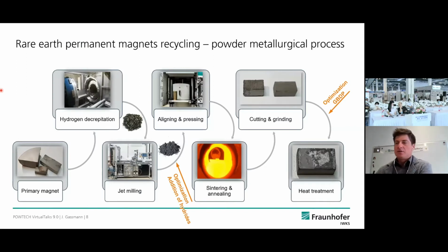So we heard a lot about powder milling and about particle size measurement today. Here the whole process is shown. Some of you might be familiar with it. For recycling, we start with an end-of-life magnet, which is cleaned and demagnetized in this case. Then one can go to the hydrogen decrepitation process, where the material is powderized with the help of a hydrogen atmosphere. Afterwards, the material is milled to a particle size in the range of 3 to 5 micrometers. Here we use two types of mill, a conventional fluidized bed jet mill and also a target jet mill for producing powders. After that, the powder is aligned and compacted, pressed to a green body, and this is sintered and annealed under protective gas atmosphere.